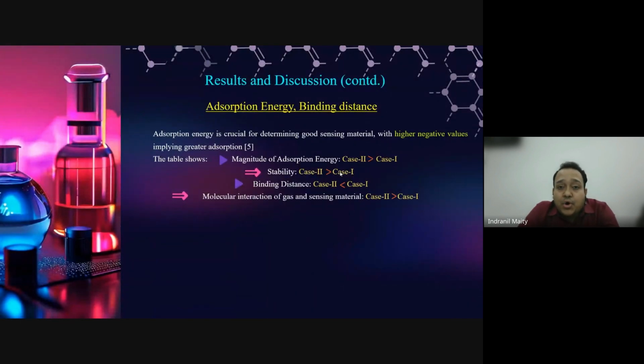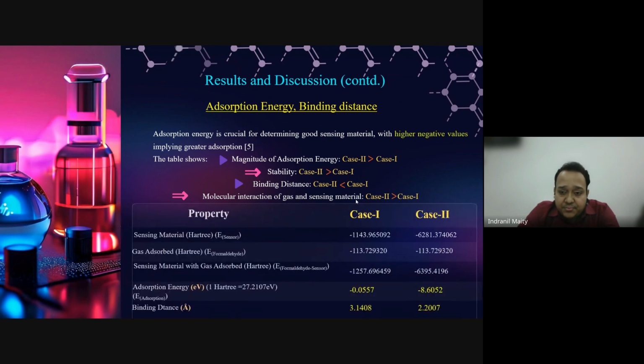Now coming to the important point for the sensing application: the adsorption energy and the binding distance. What do we mean by adsorption energy? Adsorption energy denotes the probability of adsorption of a gas or whatever molecule onto the sensing material. Here, a higher negative value denotes a greater probability of adsorption. From the table, it can be observed that the upper three rows denote the calculation of the energies, and the bottom two rows represent the adsorption energy and the binding distance values.